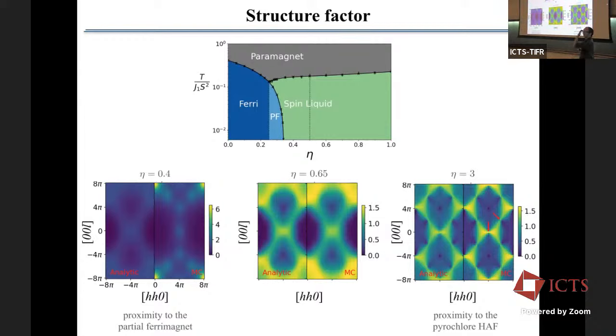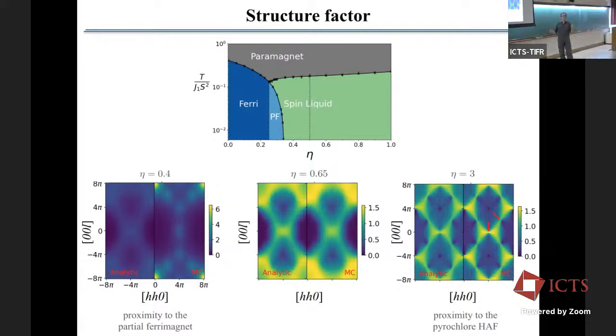This is a phase. It's not like a numerical artifact. So it's a phase. It's continuously connected to the ferrimagnet because it has the same broken symmetry, which is a Z2. Then the only difference is that in the ferrimagnet, all of the 5 spins are really long-range ordered. In the partial ferrimagnet, the spins on the outside start to have some fluctuations, and so you have some stronger fluctuations. So the bright peaks coexist with stronger fluctuations. But it is a real regime, I would say. So it's not a distinct phase, because it's the same broken symmetry. Between the two, you will have a crossover, but still it has distinct signatures.